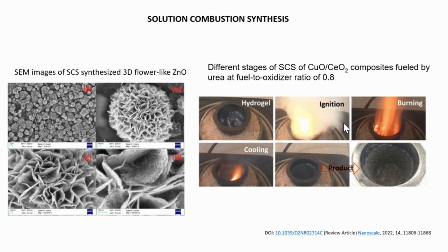The typically adopted method is to place the ceramic container containing the precursor solution on the hot plate or inside the preheated furnace at 300-500 Celsius. Heating will cause the solvent to evaporate from the precursor mixture and lead to the formation of hydrogel. The hydrogel then decomposes and self-ignites, followed by combustion, and then produces a solid product like this.